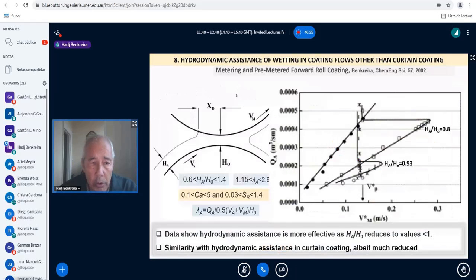And we prove that also even in a normal roll coater, if you control the feed film, normally when you have a roll coating situation, the film that comes in here is flooded. The nip is flooded. But if you control the thickness of your film coming in to make it very thin, then you can coat at much higher speed than you would coat when it is flooded.